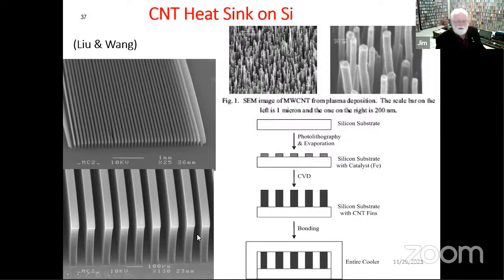Works well in principle. The problem is inside those bundles, there's no lateral contact between the nanotubes. So you've got very, very good cooling along these edges, but inside the bulk here, there's nothing going on. Now, there's another group who have grown carbon nanotubes crossways for linking these carbon nanotubes. So this problem in the original study should be solved, and this should be a viable technology again.